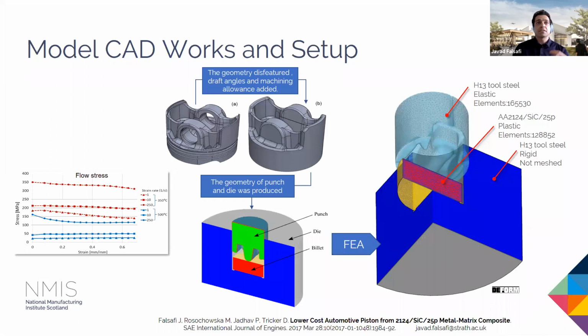So this slide shows how the initial geometry was modified. You can see in the middle. Unforgeable features were removed and draft angles were added. And finally, the toolset was created out of that. We considered the punch to be elastic so we can study the stresses and tool wear.